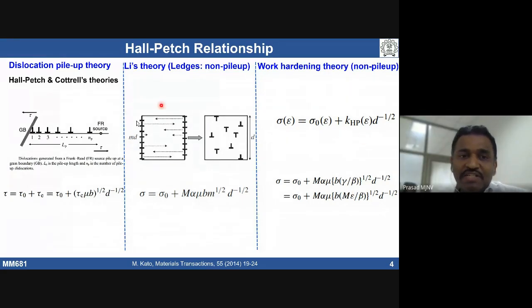Some dislocations can be trapped not only in low stacking fault energy materials, but even in high stacking fault energy materials. The only thing is that accordingly your K is going to change. The K value is going to change depending on stacking fault energy, which we have already shown in one experimental observation. So according to this theory, the amount of dislocations getting trapped, that basically the density within the grain, is going to vary depending on stacking fault energy. So that basically dictates your K, the Hall-Petch constant. Yes, clear.